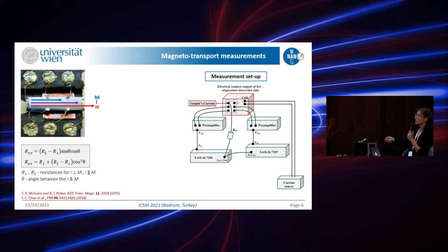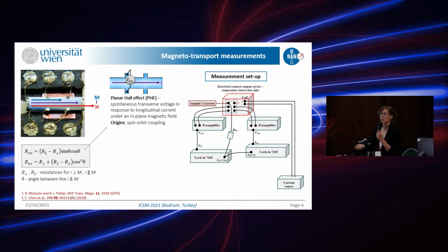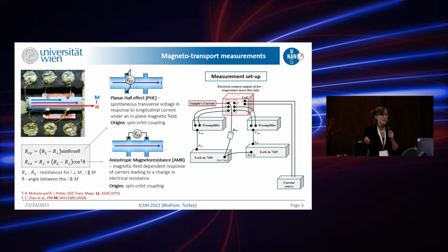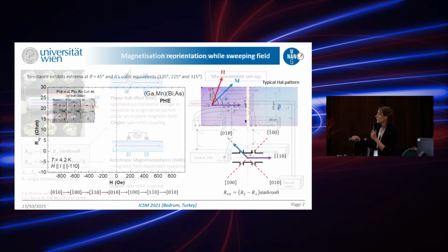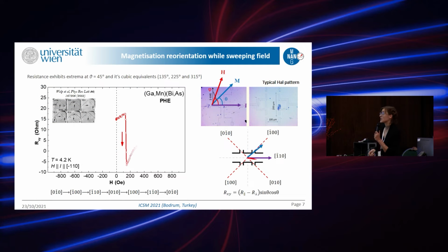transverse pair of contacts, the phenomenon will be the planar Hall effect, which is described by the first equation in the box. So it's a spontaneous transverse voltage in response to longitudinal current when we apply our magnetic field in plane, sometimes even in the absence of it. And when we measure between the contacts in the longitudinal direction, then we see the anisotropic magnetoresistance. It's a magnetic field dependent response, as you already noticed, and everything in our resistance depends on the angle theta between magnetization and current. Both origins of this effect lie in spin-orbit coupling.